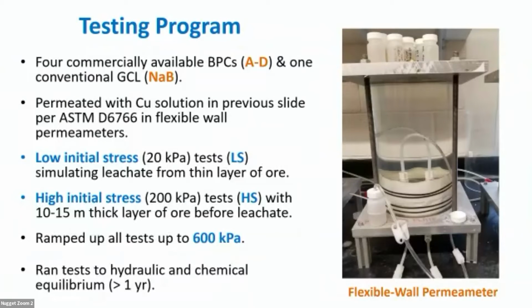So we wanted to evaluate how well they would work for a copper heap leach solution. So we took 4 different commercially available bentonite polymer composite GCLs. We created a synthetic solution. I'll show that on the next slide. And we ran tests in this device called a flexible wall permeameter, shown here on the right, which is just a vessel that allows us to apply a hydraulic gradient through the GCL vertically and to change the overburden pressure applied to the GCL through the cell pressure, that liquid-filled cell. And there's an ASTM method for that, D6766, and we followed that method throughout the different testing program.